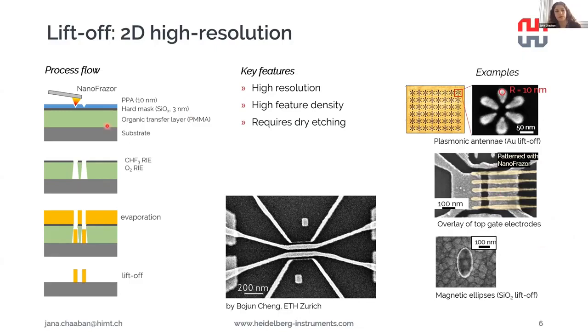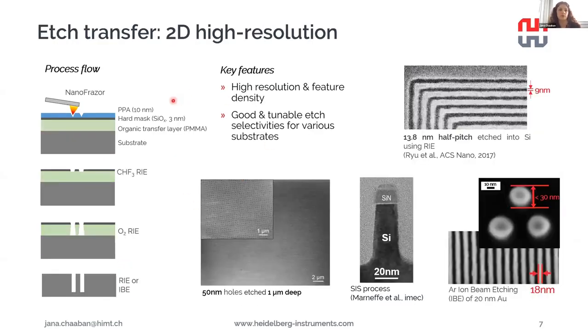Now, if we wanted to transfer these patterns to the layers underneath and etch them down, actually, we use a third technique, which is 2D high-resolution etching. And in this case, we can use the same material system. So it's essentially a transfer stack and just etch it down into the functional material of choice. And given the limited time, I won't go too much in detail into these different transfer techniques, but I invite you to watch our webinars online, which go into detail into each transfer process.